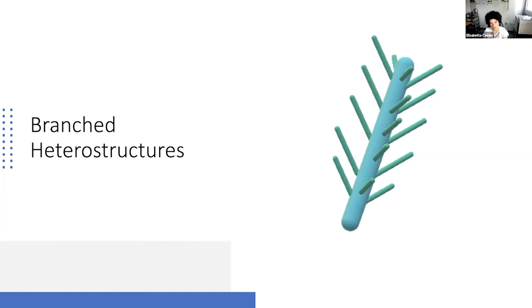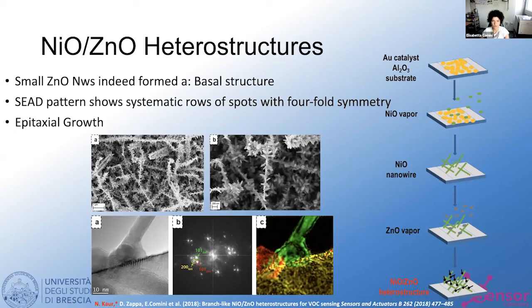We can have a branching heterostructure, like in this case that we are investigating, with the combination of nickel oxide and zinc oxide. So first we are growing nickel oxide nanostructures using a gold catalyst, and then we are growing on top of it zinc oxide nanostructures with no catalyst except the one that is present on the nickel oxide. And we can see here very nice structures. Well, the core is the nickel and nickel oxide, and the arms are the zinc oxide.